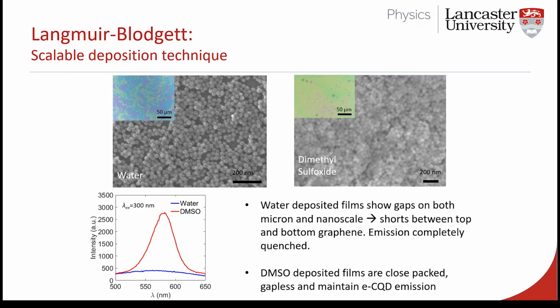So these were some nanoparticles. This was done in collaboration with a partner in Spain. And again, this was solving an issue they had about densely packing particles on the surface. Typically their process used water here, and you can see there are defects and there are problems in the packing going on here. Using our knowledge of how the materials behave in Langmuir-Blodgett deposition, we were able to change that water for DMSO and solve a lot of those problems around the packing, around the density on the surface. These were for photonics applications. So these were forming the basis of a new generation of light emitting diodes. So again, directly feeding into a manufacturing problem that these partners were having.